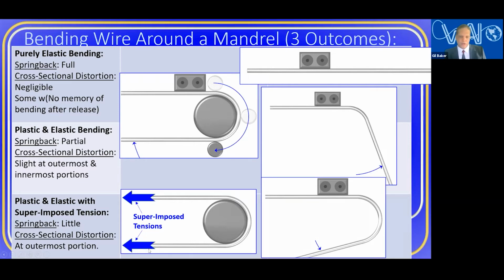What if you superimpose tension? And that's what happens in wire drawing. You're superimposing tension on both the entering and exiting wire as it goes around a capstan. In that case, there'll be much less spring back because there's more yielding. There's more yielding in tension to create a tighter wind around the mandrel, and so there's less spring back. I just wanted to illustrate that because a lot of times this is the problem we're having, where now we have a greater influence upon the wire, less spring back.